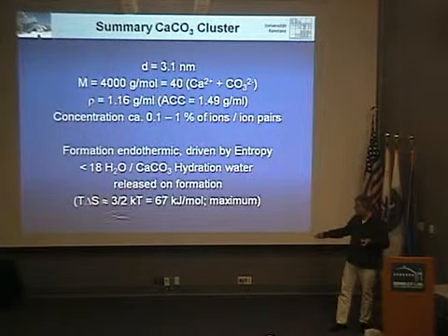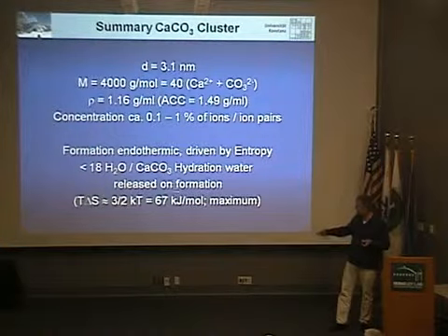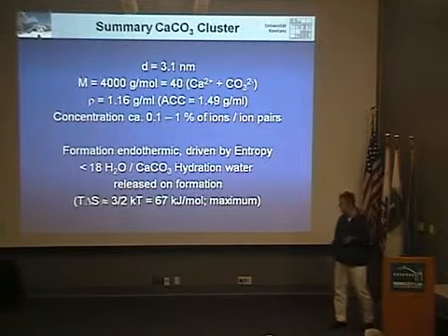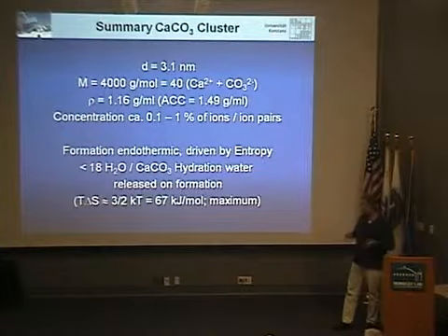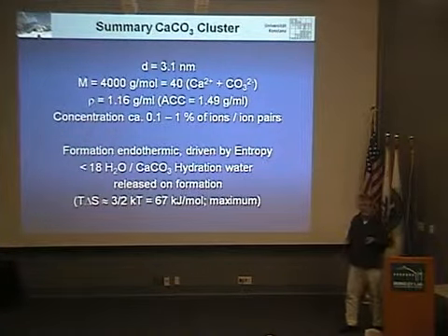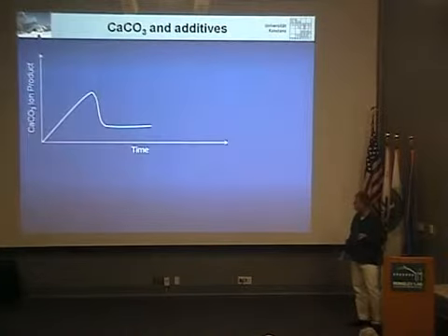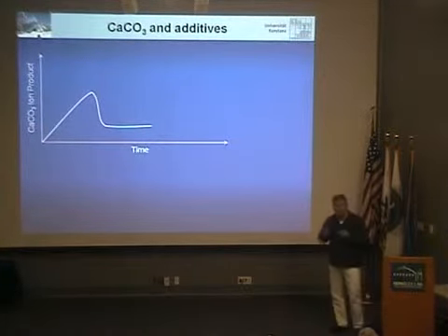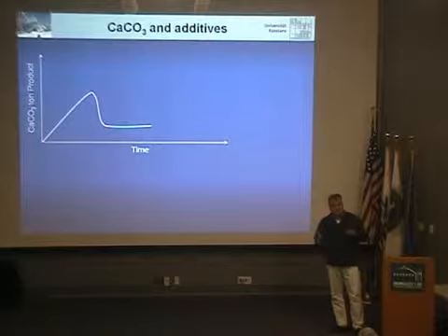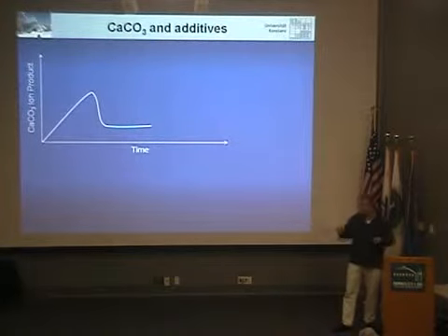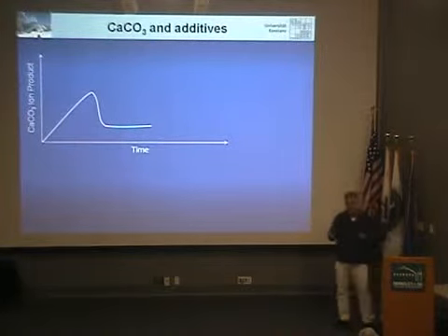If you just estimate the energy, it's quite significant. It's 67 kilojoules per mole at the maximum. So a significant entropic driving force for cluster and ion pair formation. Now, if you go from the clusters to a more complex system and start adding additives, which is the relevant case in the natural environment usually,